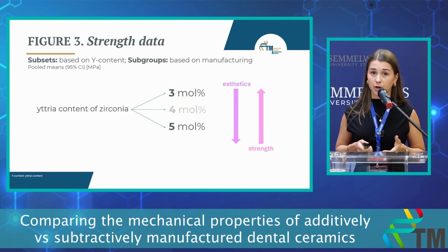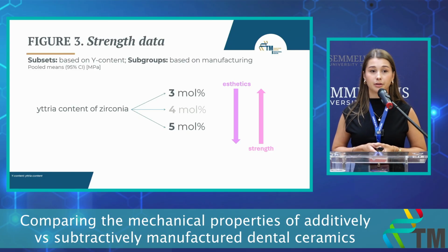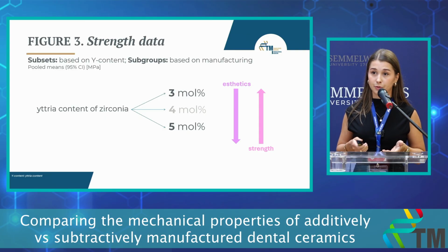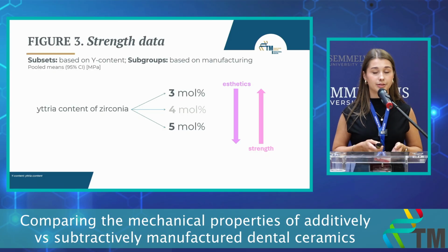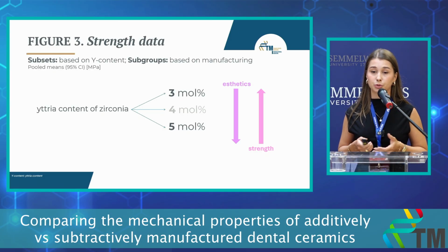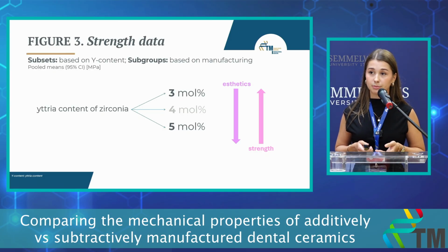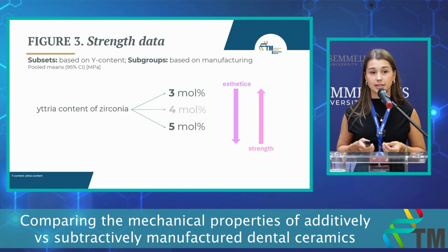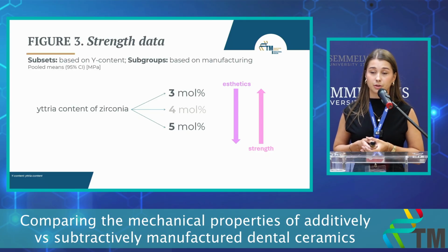We included many one-arm studies among the two arms one. Here, instead of mean difference, our outcome is pooled means. We created subsets based on the yttria content of zirconia. So dental zirconia has usually 3 to 5 mole percent yttria in it. And to put it simply, the more the yttria, the better the aesthetics, but the weaker the material. We performed subgroup analysis based on the manufacturing as well, so printing or milling.